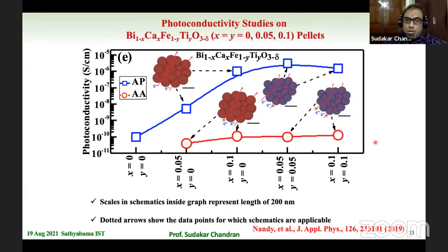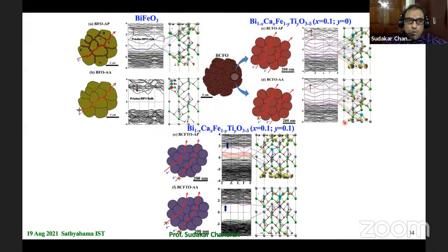One can also tailor these by just annealing them, and that's what I have shown here. If the same set of samples, if you anneal them in air, and the grain boundary conduction is shut off, therefore there's a significant reduction in the photoconductivity. How do we understand this?